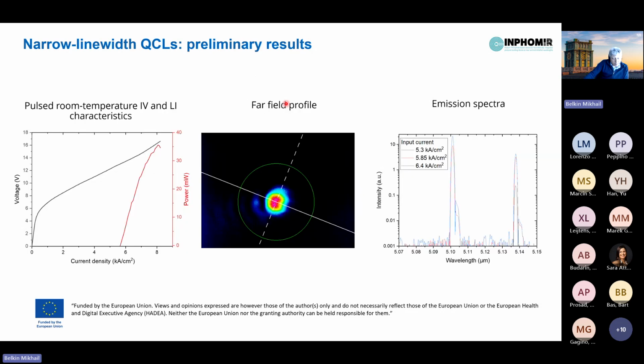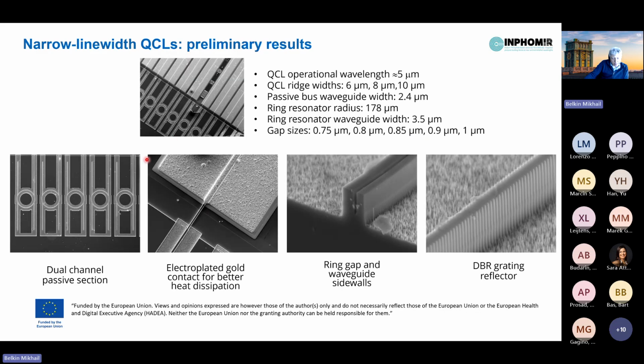So likely because of fabrication imperfections, the laser only worked in pulse mode at room temperature. The threshold current density is too high for the laser to operate continuous wave at room temperature. We need to lower it to the range of 2 to 3 kiloamps per square centimeter. This is likely due to high losses in the feedback loop. There could be some other explanations that we are working to resolve, but